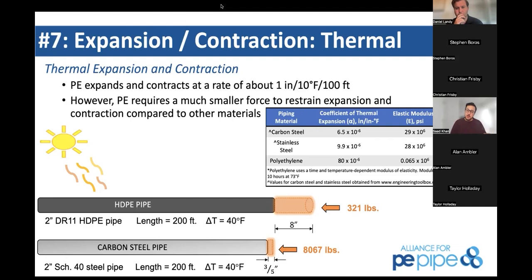Now, however, because the elastic modulus of polyethylene is so small compared to metallic pipe systems, the force required to actually prevent that thermal expansion contraction is substantially smaller, because the force required to prevent that expansion is directly proportional to the elastic modulus. And so when we actually crunch the numbers, you'll find that the force required to prevent that expansion of the polyethylene pipe is only about 321 pounds of force, whereas for the carbon steel pipe, you're looking at about 8,000 pounds of force.